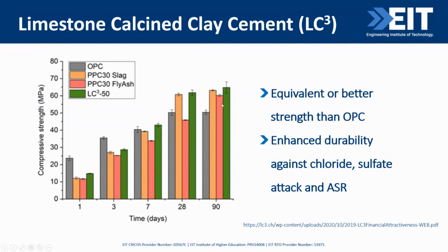And also we can see that the strength of LC3 actually exceeds OPC after 7 days, so we can see a higher strength of LC3 than OPC, as shown here. Moreover, if we compare the performance of LC3 with some other concrete using supplementary cementitious materials like slag and fly ash, so these orange and red color ones, we can see that LC3 actually shows higher early strength than other blended cements, right? So this is the strength behavior.